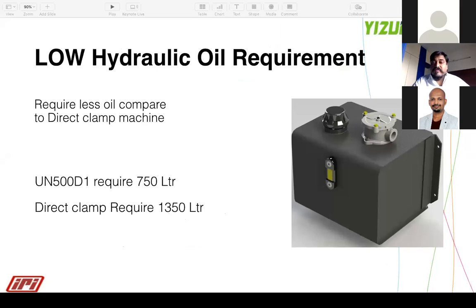Okay, and it consumes very little hydraulic oil. Typically a 500 ton two platen consumes 750 liters of oil, compared to the direct clamp at almost double, or the toggle machine, which is approximately 30% more. So the lowest oil consumption is in two platen machines.